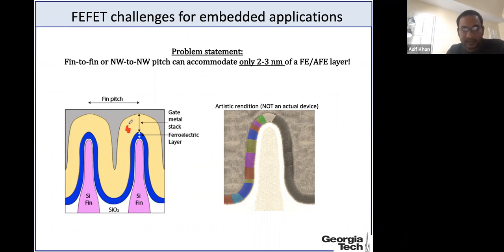so this is the gate metal stack, and this gate metal stack needs to be changed as well to crystallize this thing. So it's more like a problem where we need to look at the entire system as a whole, holistically. Like, we need to see what is the interlayer that is underneath the ferroelectric layer, what is the metal layer, what is the annealing temperature we can apply, how long, whether we can do some sort of other types of flash annealing and stuff. So these are all the questions that need to be addressed. So right now I don't think there is a right answer to how we can make it robustly ferroelectric at 2 or 3 nanometers.